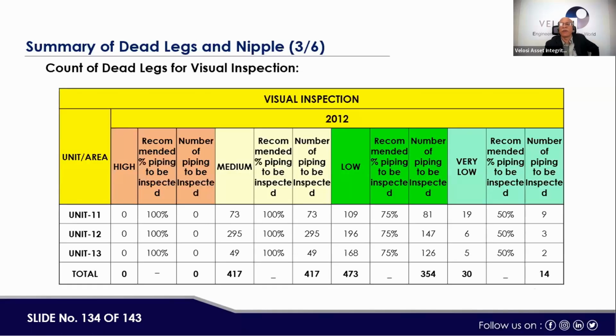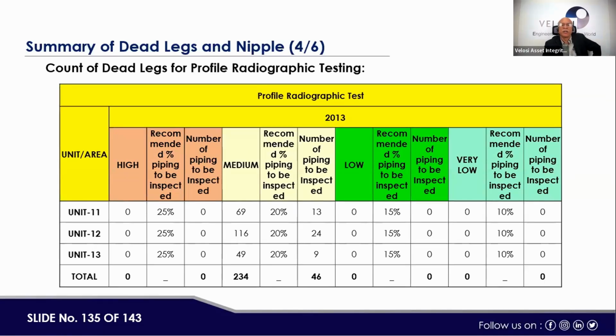Then the count of dead legs for visual inspection, basically where visual inspection was carried out: the high, medium, low, and very low. However, recommended piping to be inspected is 100% for high, and medium also 100%. For low, we have given 75%, and for very low 50%. At least visual inspection should be carried out with this ratio. Profile radiography-wise, the percentage given is 25% for high, 20% for medium, 15% for low, and 10% for very low. All are included in the profile radiography program for the small bore.